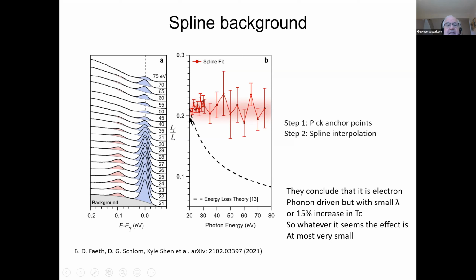However, they did it, and what they found, if they do it this way, is that it's constant. And that's exactly what you would have expected for intrinsic electron-phonon coupling. Okay, let's just assume this is correct. I don't think it is, but we'll see. What they then find is that the intensity ratio between the satellite and the main peak tells you something about the electron-phonon coupling, lambda. And if you use that electron-phonon coupling to enhance the TC that already was there because of the electron doping, which is about 40 degrees Kelvin, so just from electron doping the temperature goes up to 40 Kelvin, you would get about a 15% increase. So it would go to 46 or something like that, which means that it's very small.